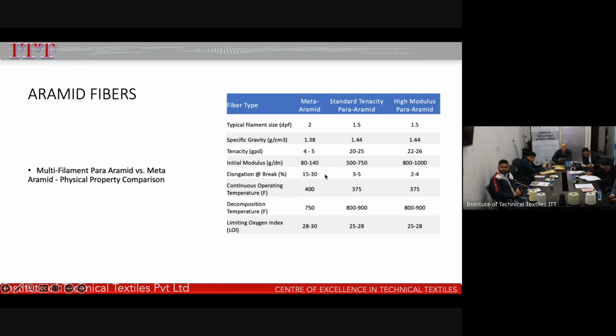Elongation at break is the second criteria. Meta-aramid has higher elongation at break, para-aramid has a lesser one. The limiting oxygen index is almost the same. Decomposition temperature of para-aramid is slightly higher. Basically, para-aramid is introduced into the fabric to give it a higher strength, and of course to decrease the char length.